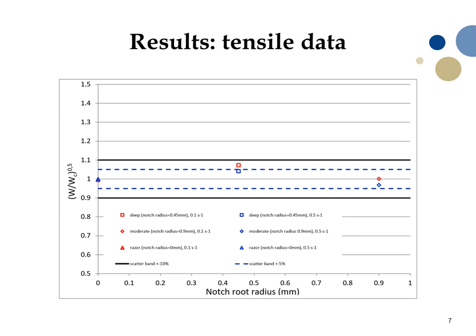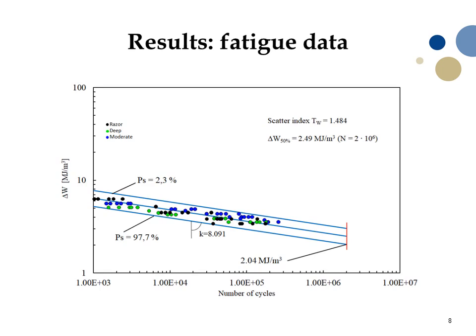The method is shown to provide accurate results regardless of the different notch geometries, both for tensile and fatigue data. The tensile strength was in fact estimated with an error lower than ±10%, regardless of the strain rate. Dealing with fatigue loading, the SED approach was able to summarize all fatigue data within a single narrow scatter band, independently from the notch geometry.